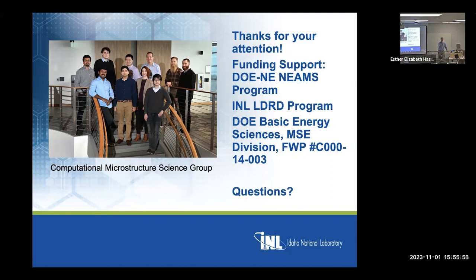Yeah. For a couple of these, I'm wondering if you applied a macro scale strain as a boundary condition, if it would affect the evolution somehow. But for that one and for really all of them, it seems like at the macro scale, you could have something applied that would affect it, but it's hard to know what that would be. Yeah. So the effect I was looking at was mostly the overpressurization or underpressurization of the gas bubbles. Yeah. Exactly. The balance between the gas bubble pressure and the surface tension, that would induce a local strain in the surrounding matrix. Yeah. So I found it didn't have a particularly big effect. I did not look at macro scale strain effects though.